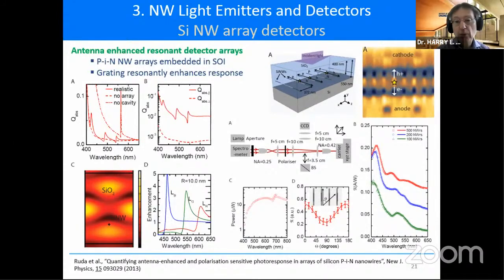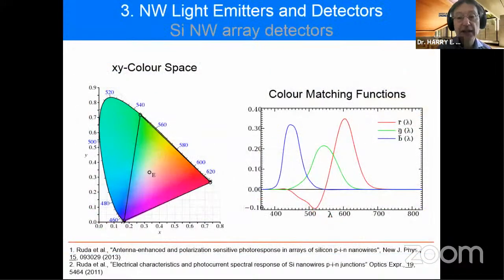But in our case, what we were interested in is the fact that by tuning the spacing and width of these structures, again, we could tune the color response. And so you can see in the second figure at the bottom the color response, but in fact we can tune effectively indefinitely, because we've developed color matching functions over the whole of that XY color space.